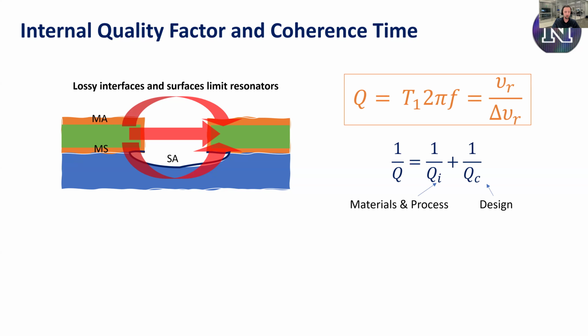So they're just looking for this sharp peak. How much does it diverge from what they designed? If it diverges a lot and it's much lower and flatter and wider and broader, a lot of materials loss is going on. All right, well, we can separate this out. We'll separate it out as the participation ratio of these electromagnetic fields, which depends on design, of course, in the substrate, the superconductor itself, and the surfaces. And then a quality factor for those, an inverse loss tangent. In practice, this is totally dominated by the surfaces. And so it's just these three interfaces we care about.